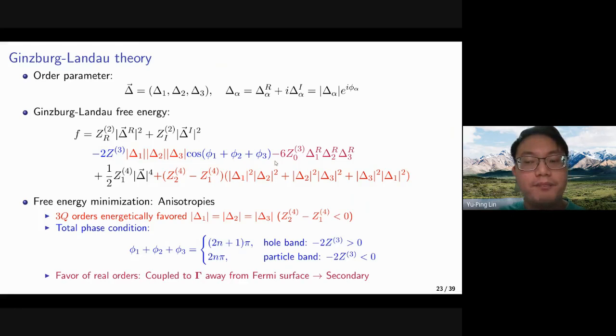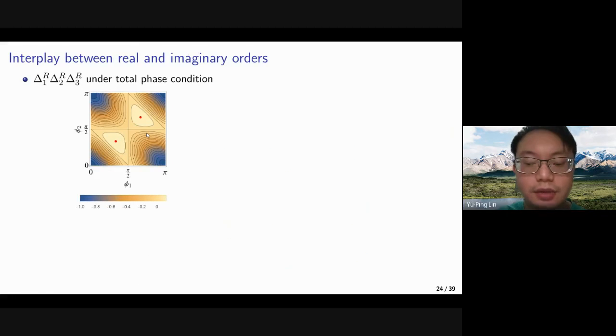So the third degeneracy breaking term is the secondary term here. This term, as you can see, couples only the real orders. So it will favor the real orders. However, this term is coupled in addition to the, besides the saddle point, it is also coupled to the gamma point, which is away from the Fermi surface. So at low energy, we know that it should be a secondary term compared to the other ones with only the saddle points. So we should now understand what are the ground states in terms of the free energy minimization.